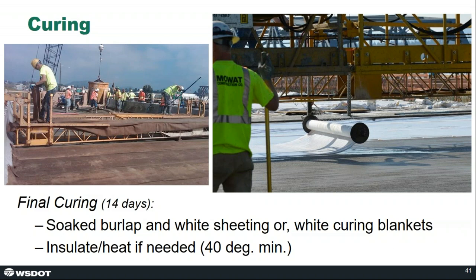There's also other products out there that are purpose-built for concrete curing. The photo on the right shows one system. It's just a one-piece curing blanket that's saturated and white for reflectance as well. The contractor has rigged up a pretty good system here where they just unroll it on the bridge deck from the spool, and they've got a little sprinkler system to saturate it as it goes down. This sort of material is very similar to a diaper, but it retains moisture better than the burlap. So if you've got a bridge on a steep slope, you tend to lose some of that burlap water as it drains away, whereas these curing blankets can retain that and prevent the contractor from having to collect as much of that cure water runoff.